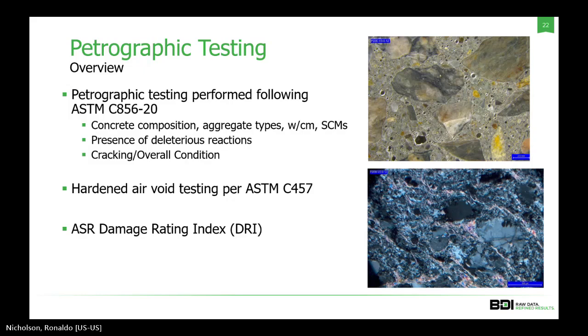For the petrographic testing, the petrography was performed following ASTM C856, where we were looking at the composition, aggregate types, water to cement ratio, SCMs, any presence of deleterious reactions, and cracking and overall condition, as well as hardened air void testing per ASTM C457 and the ASR damage rating index. And we'll go over a little bit of what that means in the next few slides.